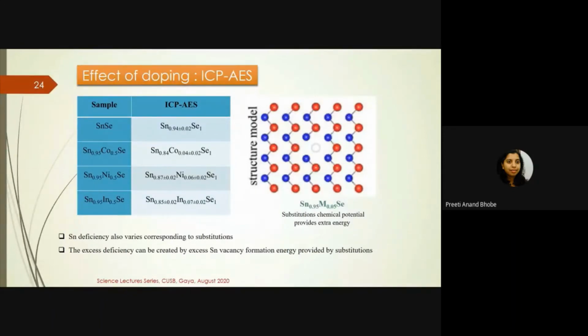But what happens with cobalt, nickel or indium addition is that the total does not add up to this 94 or 95%. We see a further decrease in the cations. So it implies that we have cation vacancies in this system. When you try and dope these materials, it leads to cation vacancies or point defects in this material. And because of these defects, there will be scattering of phonons, and that scattering of phonons is what is bringing down the thermal conductivity to a large extent. That we can understand for the thermal conductivity.